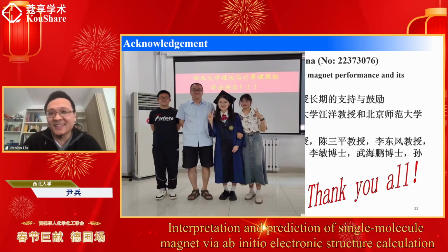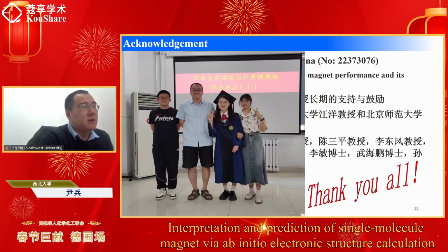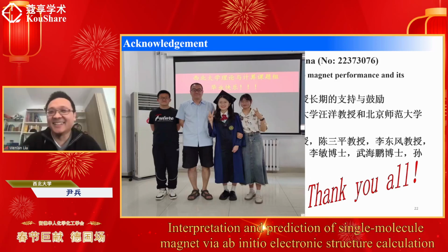Yes, the calculation is very expensive, because we cannot use DFT to treat this kind of system, which has a significant amount of multiconfigurational character, and CASSCF may be the necessary one. But for the systems studied by me, they contain only one lanthanide, so the active space is only seven orbitals. So that is okay for me.